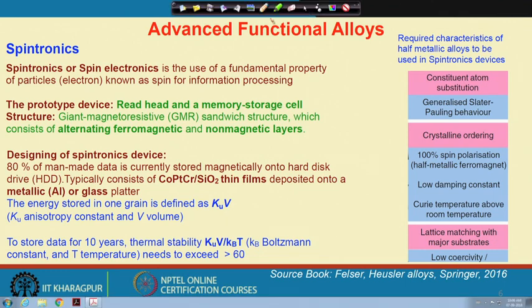So, as an example I can tell you, we discussed cobalt platinum for magnetic storage. You may recall here this is a cobalt platinum chromium alloy and a silicon dioxide thin film, which are sandwich type of structures that are made for devising those spintronics applications. So, so far for such a design 80% of the man made data today are stored magnetically in the hard disk or hard disk drive we call, and typically they all consist of these cobalt platinum chromium and silicon dioxide thin films that are usually deposited on a metallic aluminum or glass platter.